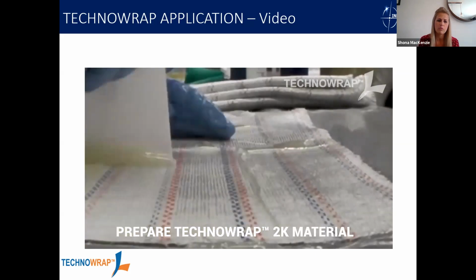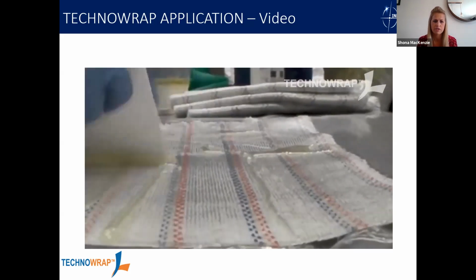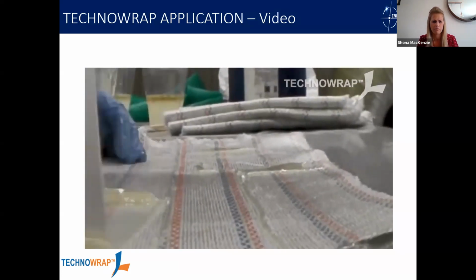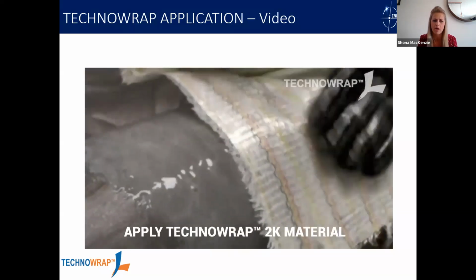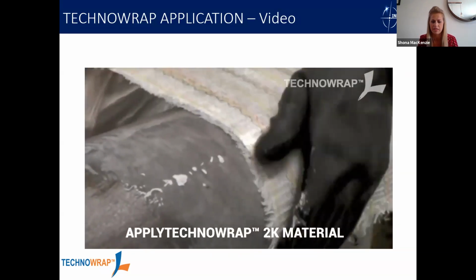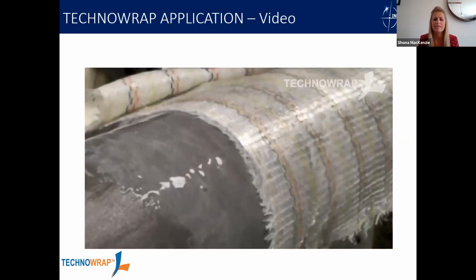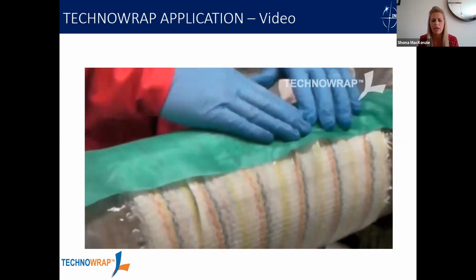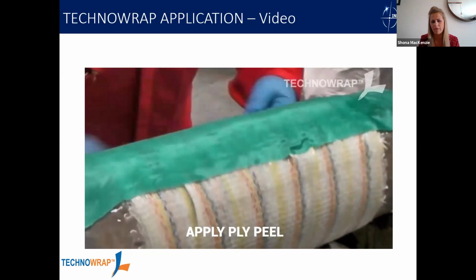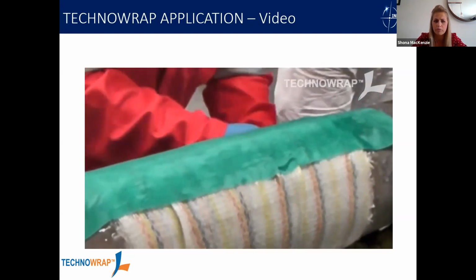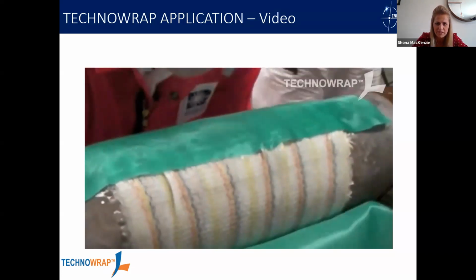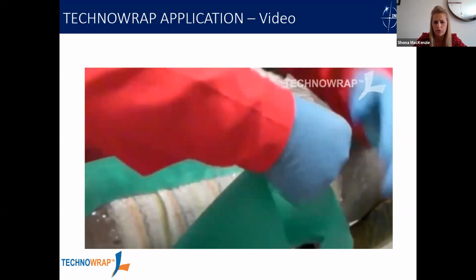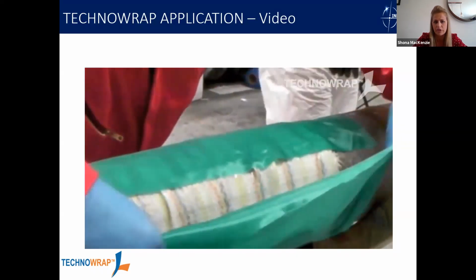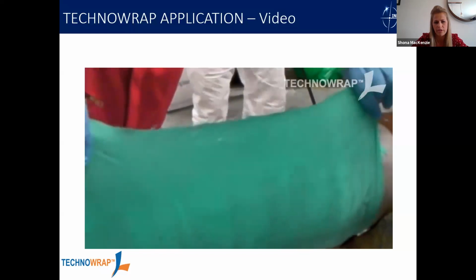And what we do is we wet the resin system into the cloth itself. So that resin system is in two parts, part A and part B, and they're combined and measured in the right quantities. It's wet into the cloth, and then that is applied over the pipework. Then what we do is we apply a layer of peel ply, which is the green stuff that you can see there, and that is to allow for the application of the next layers, to ensure that there's good adhesion